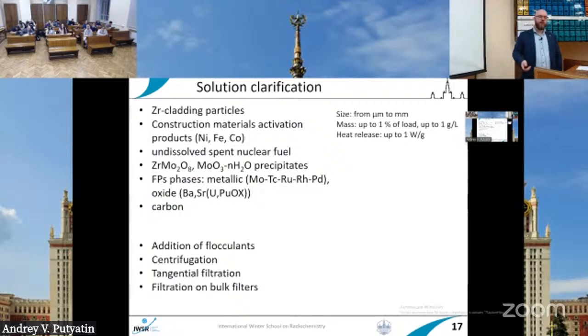And it is different components of the spent nuclear fuel that form metallic phases, like epsilon phase, that consists of the noble metals with some fraction of technetium and molybdenum, and these noble metallic particles are hardly dissolved in nitric acid, so there are additional procedures that can be done, but ruthenium, for example, is very difficult to dissolve. And carbon also can be not oxidized completely, so there are particles of carbon.